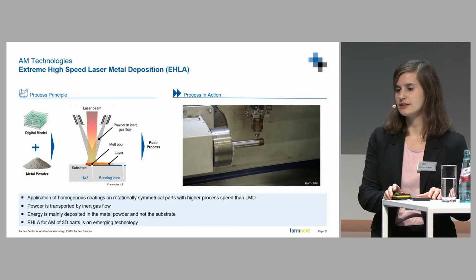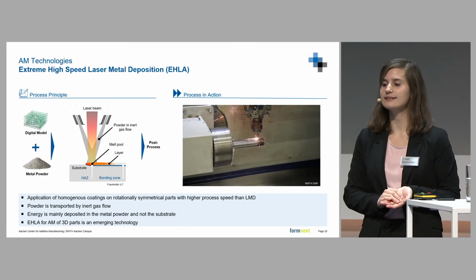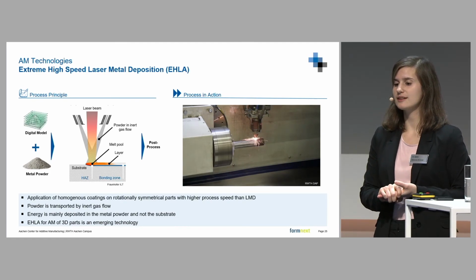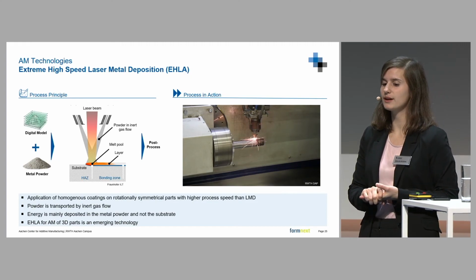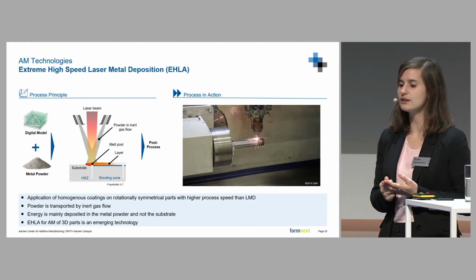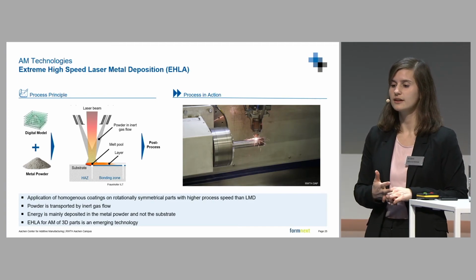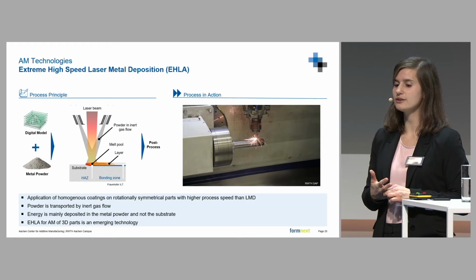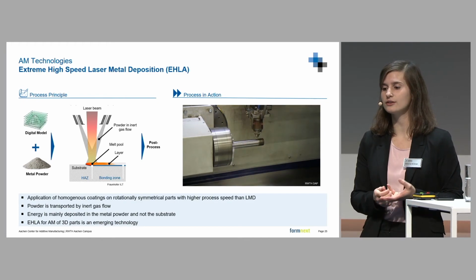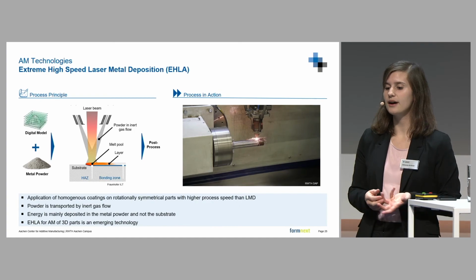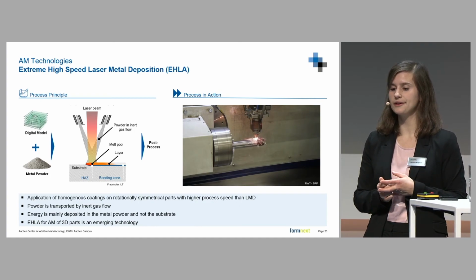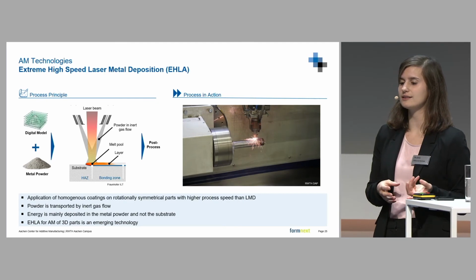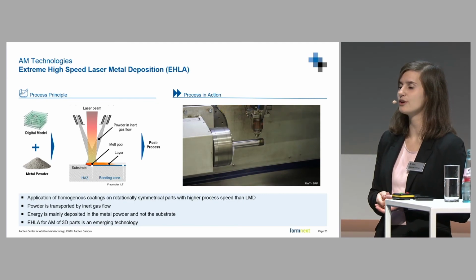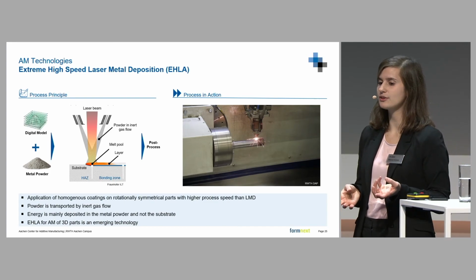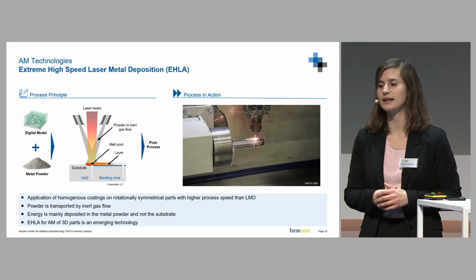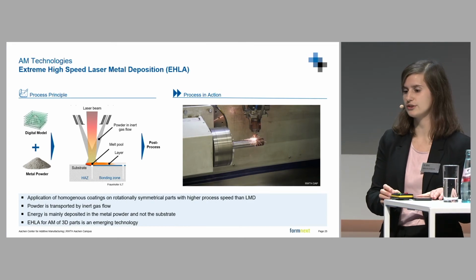So let's take a look at EHLA, which is extreme high-speed laser metal deposition. It's pretty much the same principle as LMD, but the EHLA process works only for rotationally symmetrical parts. It has higher process speed than LMD, and you can apply very homogeneous coatings on those rotationally symmetrical parts. Again, the powder is transported by an inert gas flow, and EHLA is starting to come up more when you look into coating applications within AM, so it's a technology with high potential that's expected to be used in industry more in the future.